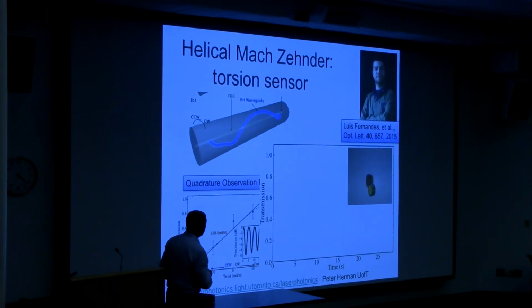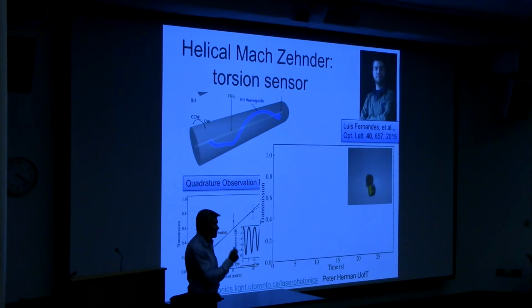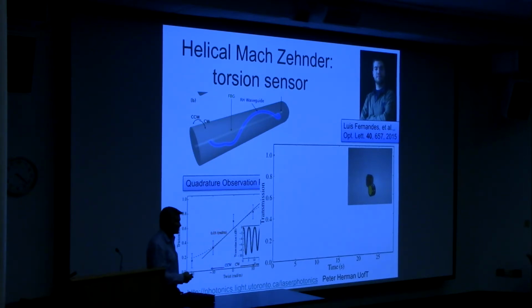So normally this would be a longer path, right, because it's spiraling around. But the refractive index in the glass is lower than in the core waveguide, so it actually does the opposite of what you think. But in the end, there's a net optical path difference, and that gives the cosine wavelength pattern. And then when we twist this fiber, that helical path is getting longer or shorter due to the twist. That's torsion. And so this is a torsion sensor.